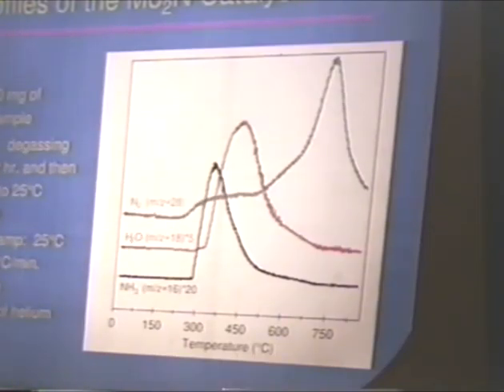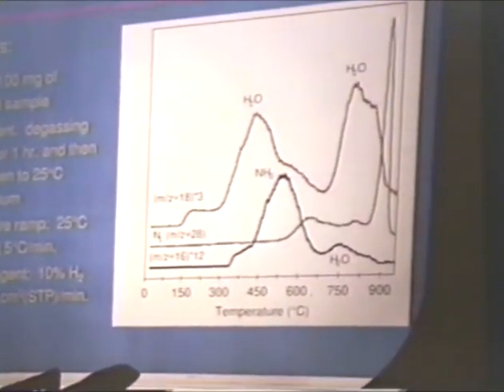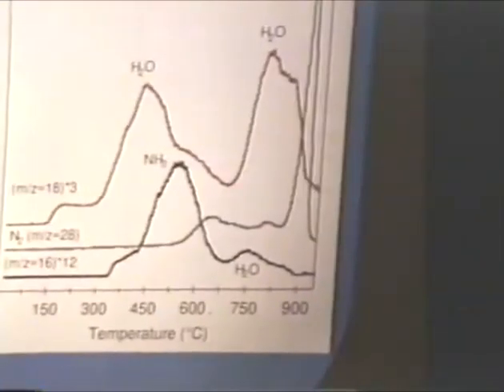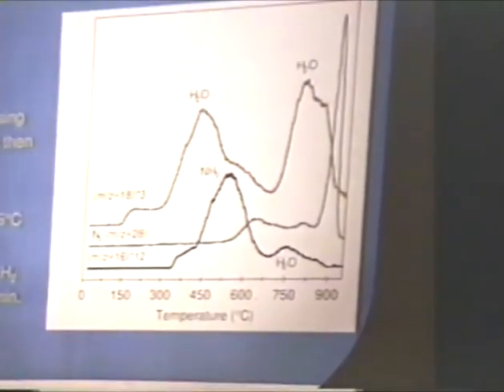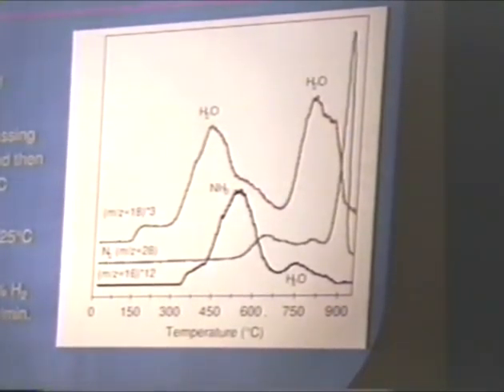We also see, although in much smaller intensity, some ammonia and water desorption in this experiment. Now, through these experiments, we determined that to get rid of all of the adsorbed ammonia and water species, we had to degas the sample at least at a temperature of 500 degrees centigrade, and that was a basis for our pretreatment procedure in our TPR experiments, where the catalyst was first degassed at 500 degrees centigrade to eliminate all of the adsorbed ammonia and water species. This way we were able to differentiate ammonia and water forming as a result of the reduction reaction versus those that have been adsorbed and desorbing on the surface.